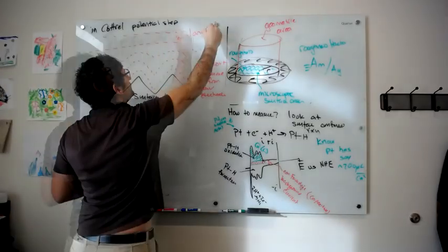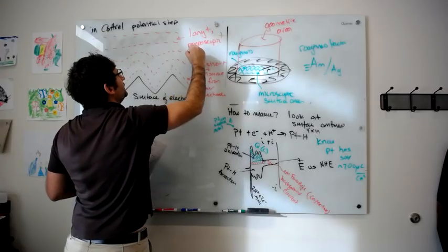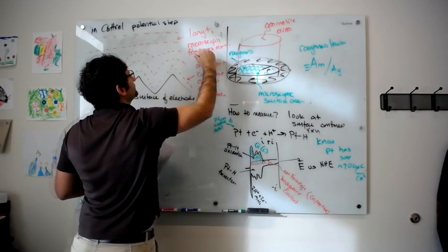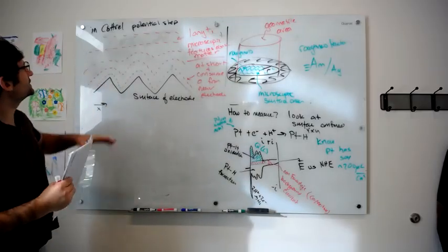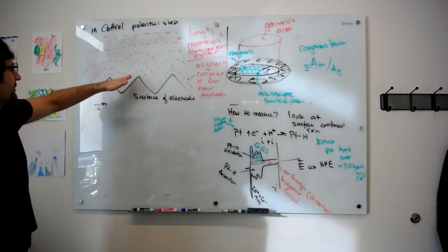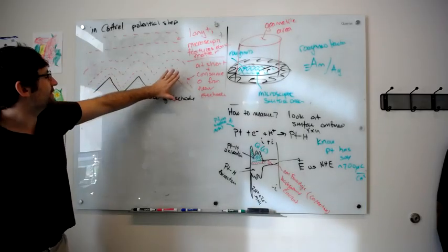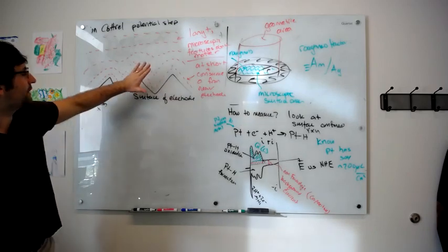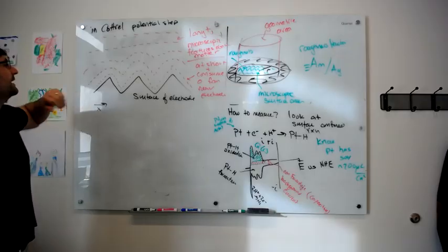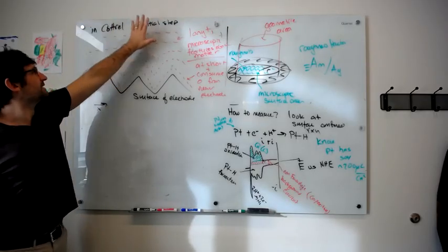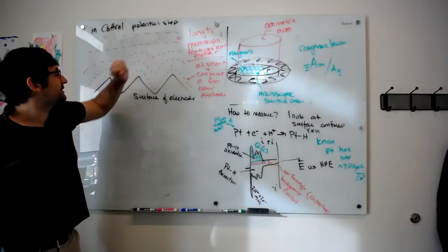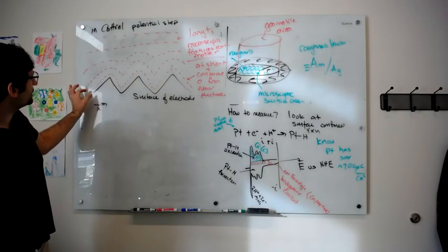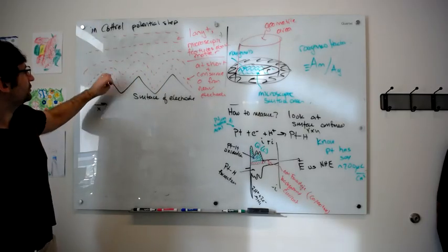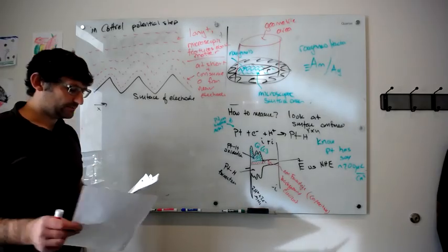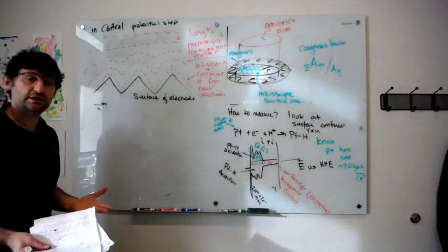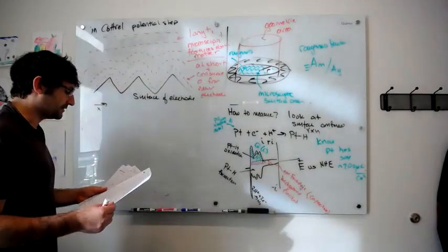So at long t, microscopic features don't matter. And they don't matter, if you think about it, because if you're far away from the electrode surface, you don't care that there's this microscopic geometry, because the whole surface is acting as a boundary condition, and the whole surface is consuming O only as fast as it can diffuse from far away. And it doesn't matter if there's more surface area down here, you still have to pull from the same volume element of electrolyte, your O, to turn into R. At very short times, you actually have more electrolyte that's close to the surface, and you can actually pull more O.